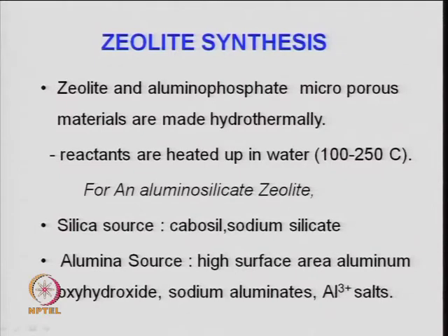Basically, whether zeolite, aluminophosphate, the mesoporous material I mentioned, or molecular sieve material, they have one kind of process, which is known as hydrothermal synthesis. That is, in the presence of water and under autogenous conditions, you allow the raw materials to come in contact and form a kind of gel. The formation of gel is very crucial, because the structure building agent which you add and the type of gel will decide the framework of the zeolite. Then the nucleation and crystallization which take place during this process give you the size of the crystals. So, that is also equally important.